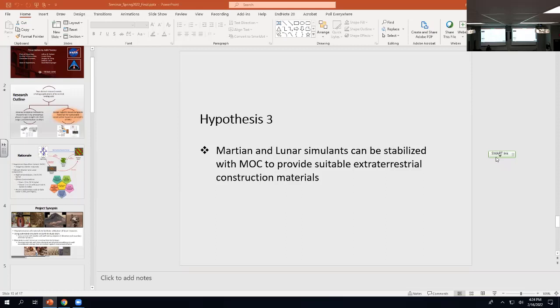I would suspect they're lighter because the magnesium oxide cement reaction is not just one thing I sort of missed to mention. It is a highly exothermic reaction. When I mix these samples, they usually get warm to touch while I'm mixing them. And there's a lot of research that's been going on in order to control how fast the reaction occurs. So that's why it's very viable for 3D printing, because it can cure as you're printing. So you're not waiting days before each layer of sample that you're adding. So yeah, because it's more reactive, you'd expect more bubbles to form, and I think it is generally more porous, so it is lighter.